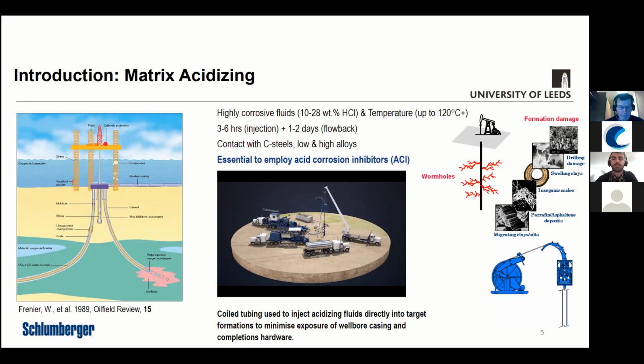But you also get an additional flow back period after the injection period, which is essentially where the unspent acid that's been used in that procedure will flow back into the well over the next couple of days, and that would make the fluid environment more corrosive because you've still got some of the acid remaining in there. So for the purpose of what I'm presenting today, we're just looking at the injection period, but we've done some work in the past with Schlumberger looking at using the flow cell to evaluate flow back as well, if that's of interest to anybody. But today, just focusing mainly on the injection period.